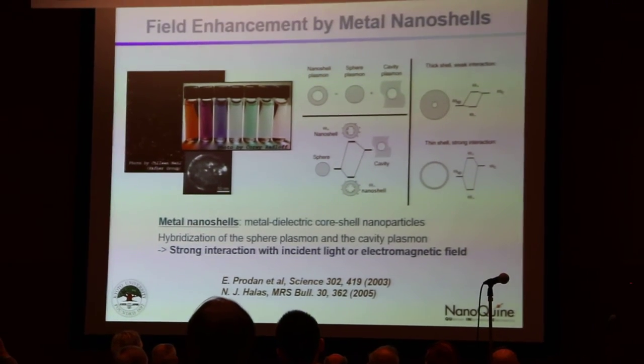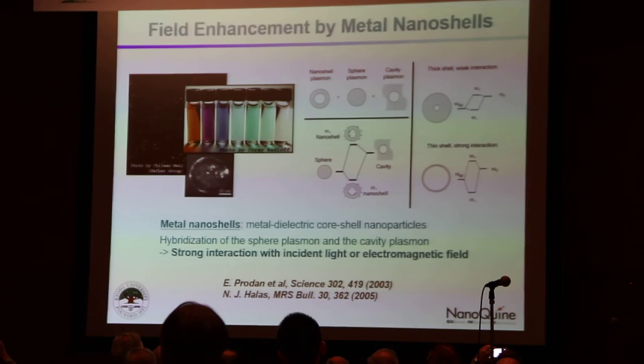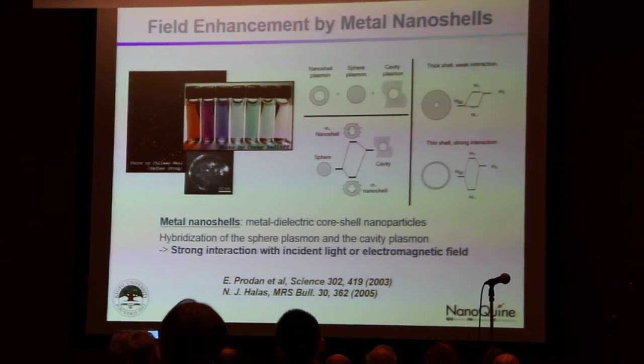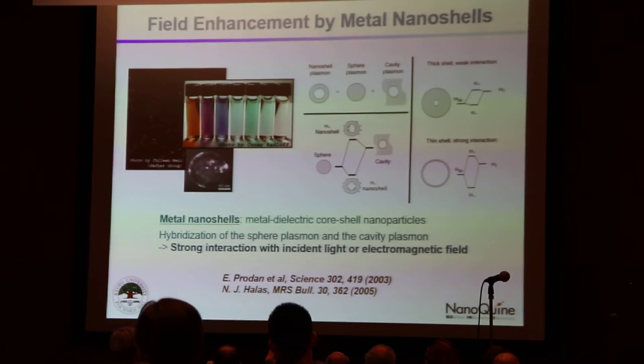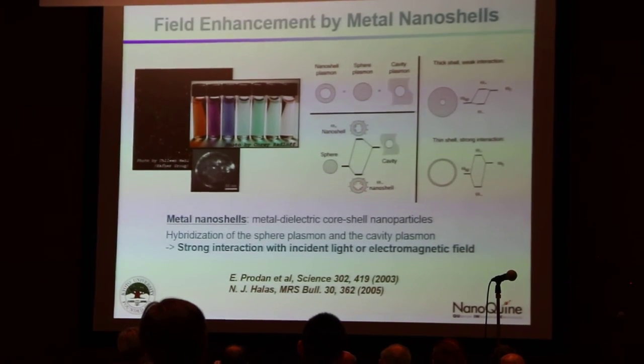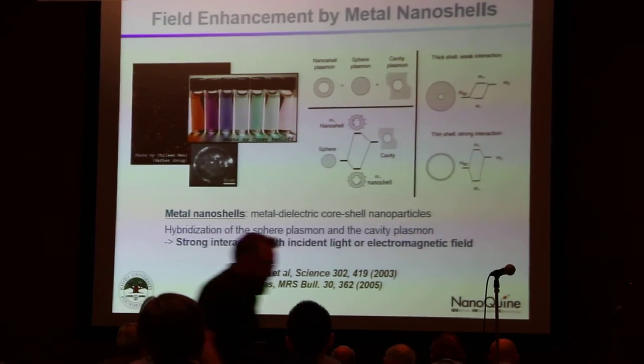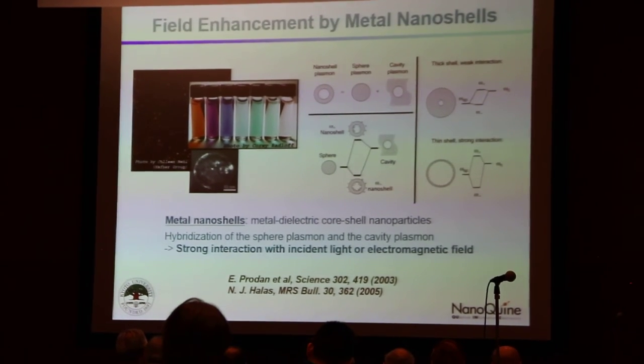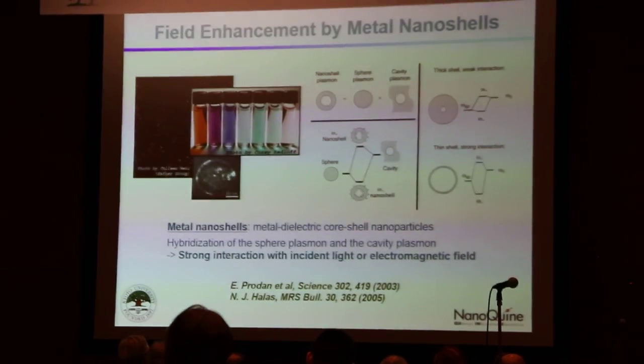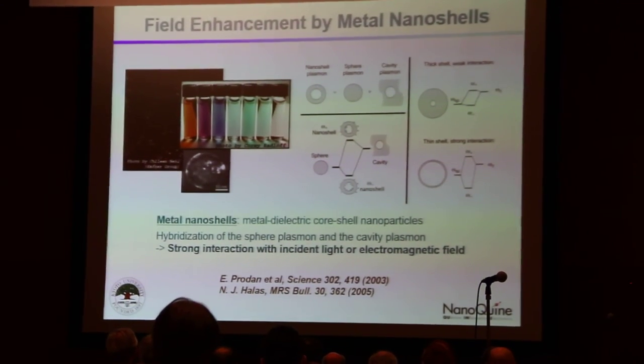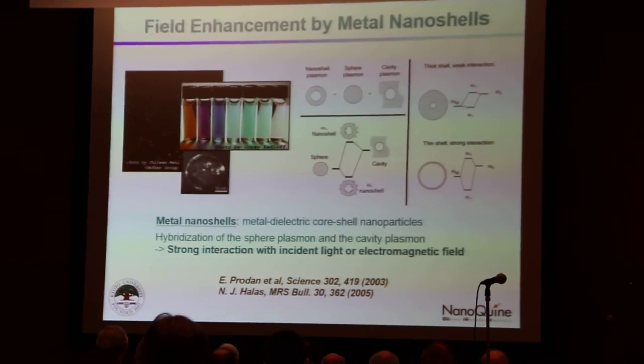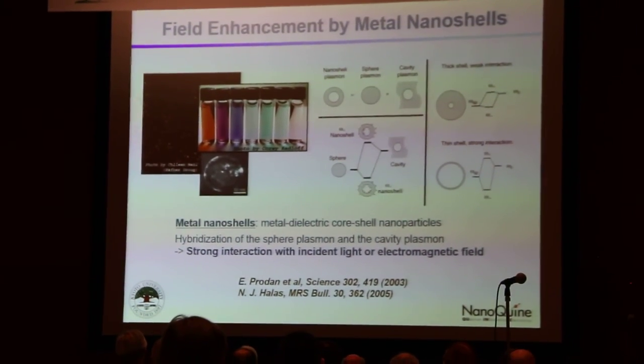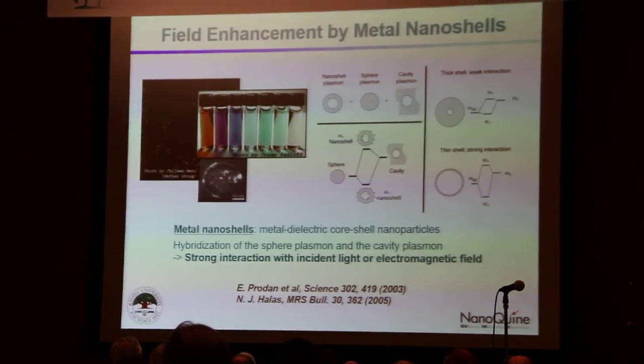So far I have talked about simple spherical metallic nanoparticles, but let me switch gears and talk about metal nanoshells. Nanoshells consist of a metallic shell and a dielectric core — core-shell type nanoparticles. For this system of material we can have even higher field enhancement effect thanks to the hybridization of the intrinsic spherical plasmon mode and the cavity mode.